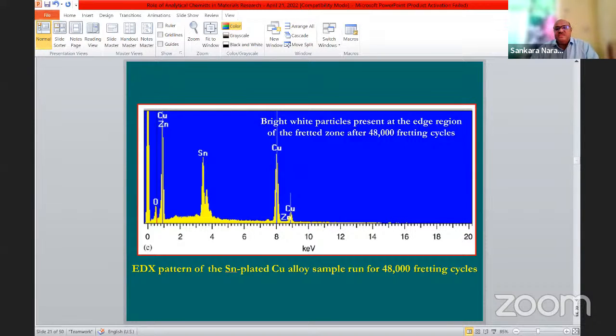Here we have taken the entire fretted region. You can see that a lot of tin is there because we have taken the entire sample area, and the damaged area is limited to only 200 or 500 microns. So there is plenty of tin in the entire fretted region, and the copper and zinc are from the base metal, and there is a small amount of oxygen.